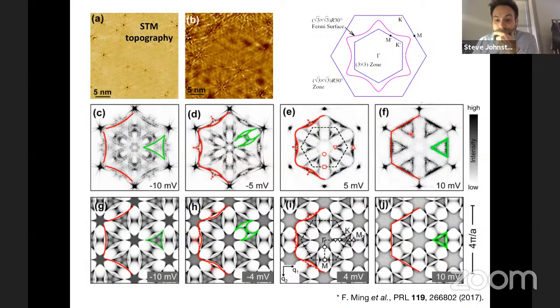Right. But I do find it very interesting because I put in the chat a reference to some of the earlier work we've done where we carefully treated this one impurity in a correlated host. And we find substantial effects. Now, I was always dreaming about the possibility that STM can look at this. Unfortunately, most models where they do STM, they are either multiple band models, or they have all the complications of oxides that you talk about, or there is always something on the Mott organics that cannot be done. So it's not a single band model. And there are a million reasons why it was impossible to find a simple setup where you can do a single band model with correlations and test these ideas.